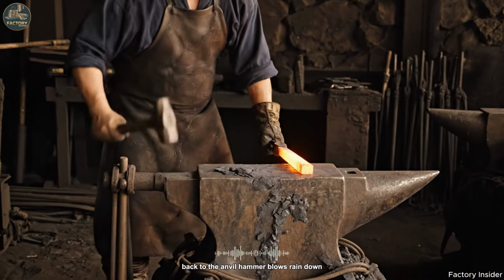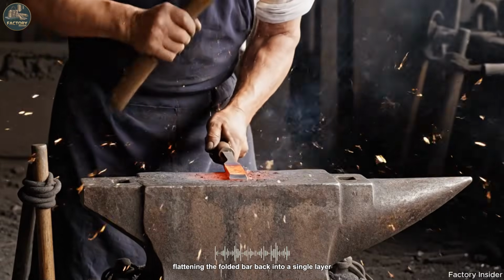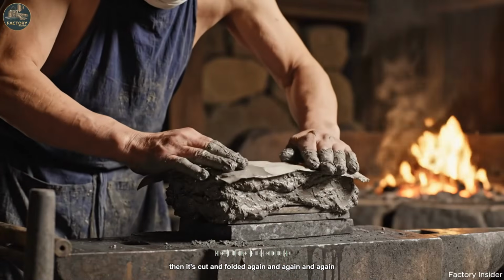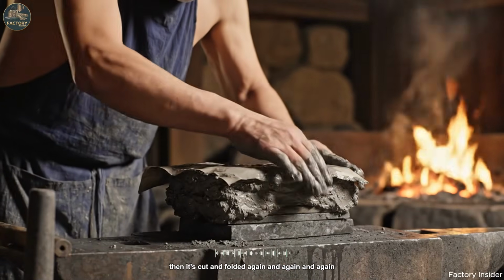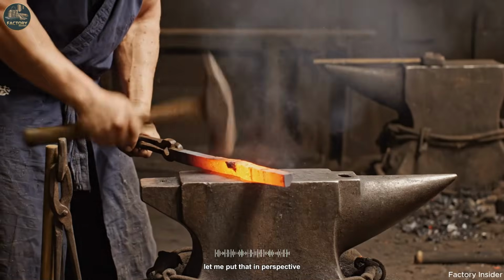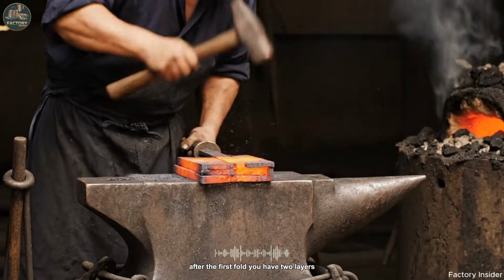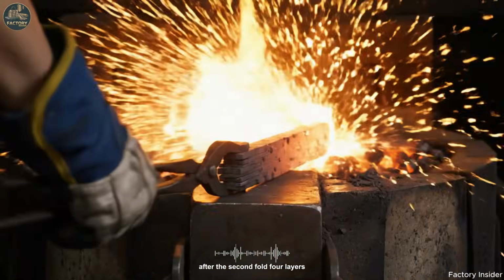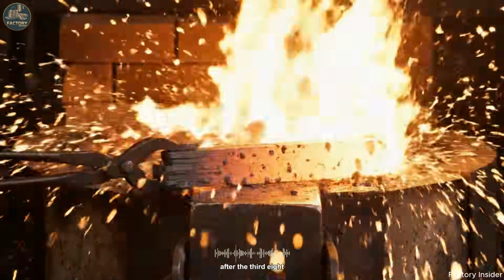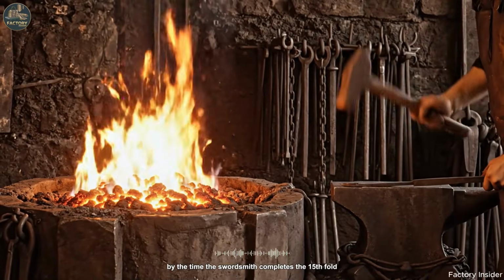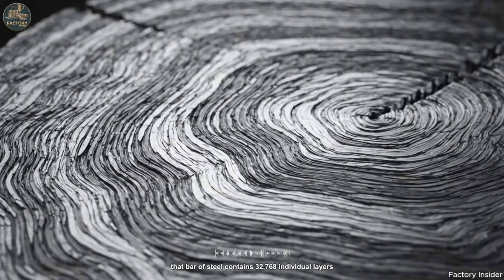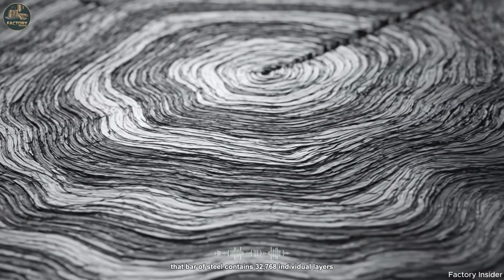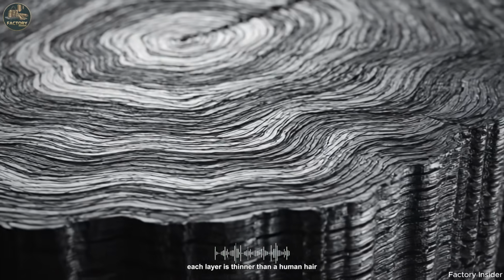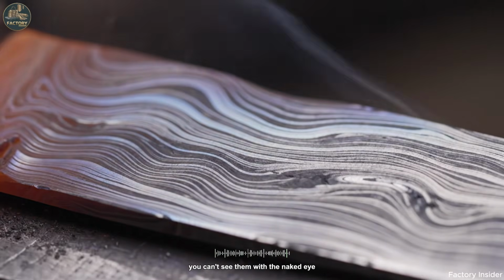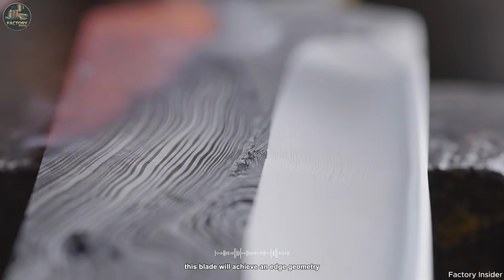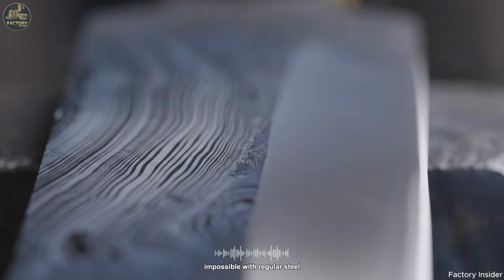Back to the anvil. Hammer blows rain down, flattening the folded bar back into a single layer. Then it's cut and folded again, and again, and again. This process repeats 15 times. Let me put that in perspective. After the first fold, you have 2 layers. After the second fold, 4 layers. After the third, 8. By the time the swordsmith completes the 15th fold, that bar of steel contains 32,768 individual layers. Each layer is thinner than a human hair. You can't see them with the naked eye, but they're there. And they're the reason this blade will achieve an edge geometry impossible with regular steel.